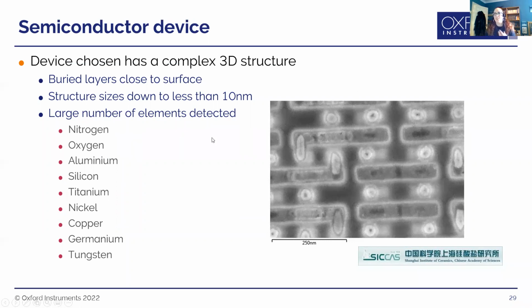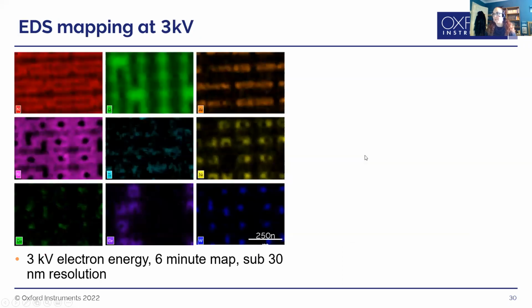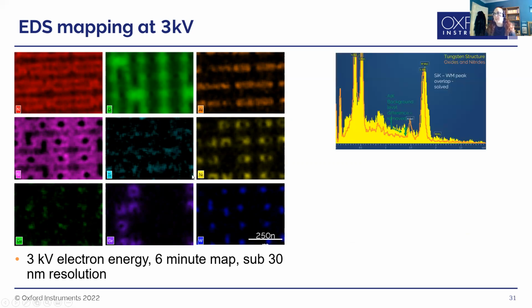So here we've got a semiconductor device, and this is really nice to show you some of the resolution advantages. Like with a lot of life science samples as well, it's got many different elements within it, but it's got really fine structure. And if you look at 3 kV, we're getting some really nice structure through. So we're getting less than 30 nanometer resolution in our maps, which is pretty good.